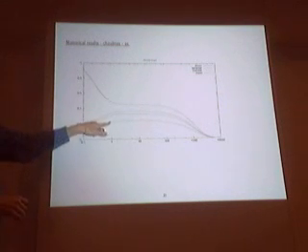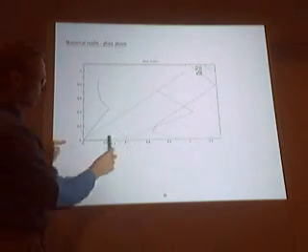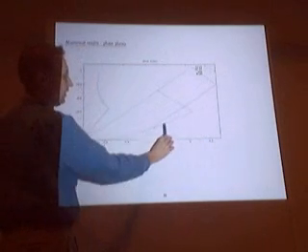The enantiomeric excesses, we put in a small initial perturbation. That small perturbation grows, and it looks like it's reached steady state, but if you wait long enough it goes back to racemic, which is not very nice. These are sort of phase planes. I don't know if these are useful, but this is the number of clusters and the mass of clusters. It very quickly reaches some point. This is where there's virtually no stuff left, no monomers or dimers left to react with, and so very quickly you get to this state, and then you evolve very, very slowly towards this racemic state.